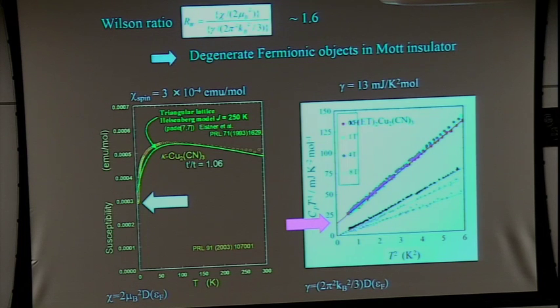But in usual correlated electrons, the susceptibility is generally enhanced somewhat over the susceptibility expected from the gamma value. So in real materials, the Wilson ratio R_W is 1 or 2. This means this spin liquid insulator looks like a metal, because the Wilson ratio is 1.6. It's a very conventional value for a Fermi liquid, but this is an insulator. So this is a very striking result, because despite the insulating state, it seems that there is some fermionic stuff in these materials.